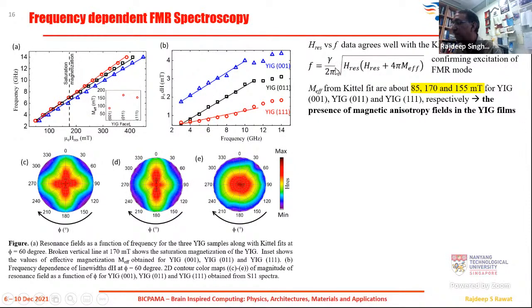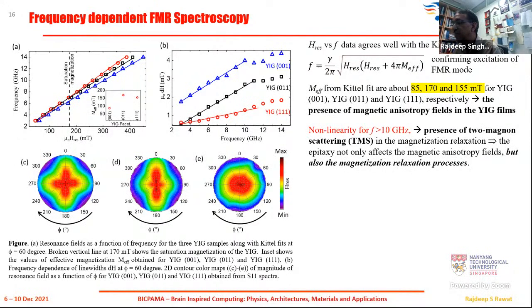Using this Kittel equation fit, you can calculate the effective magnetic field for these 3 different orientations. We found the values listed here, which are less than the saturation magnetization of YIG, typically around 175 millitesla. You can see there is a significant difference, particularly for the 001 orientation and 111. All of them have quite some difference. That means there is an anisotropic field present in these crystals, which is causing the difference. After that, as I mentioned, we focused on the angle-dependent FMR.